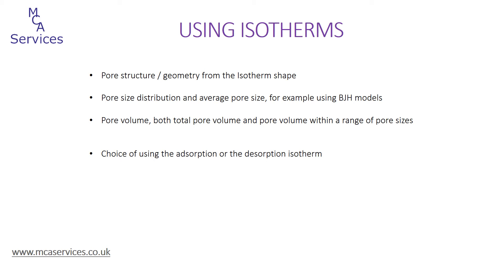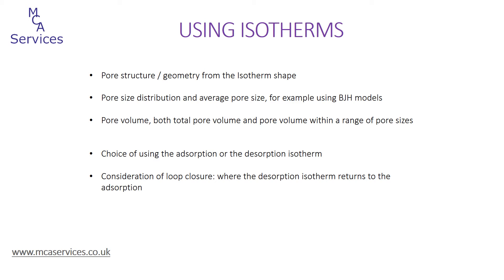A final point to note is that when using desorption isotherms we have to be aware of loop closure — that's the point at which the desorption isotherm returns to meet the adsorption isotherm. In particular, hysteresis types 3, 4 and 5 show a sudden reduction in the desorption volume, and we'll discuss that a little bit later on.